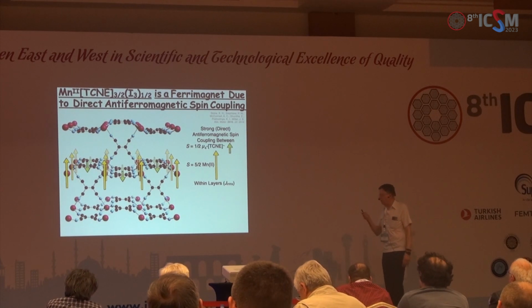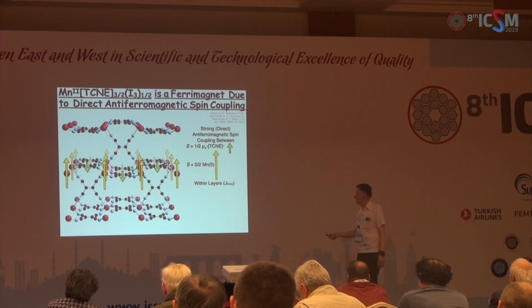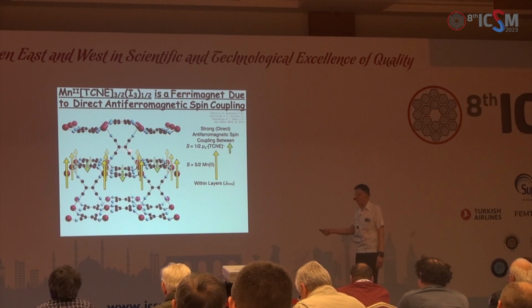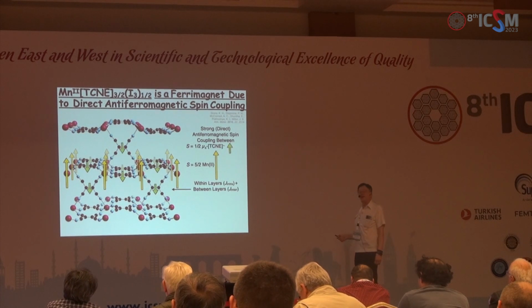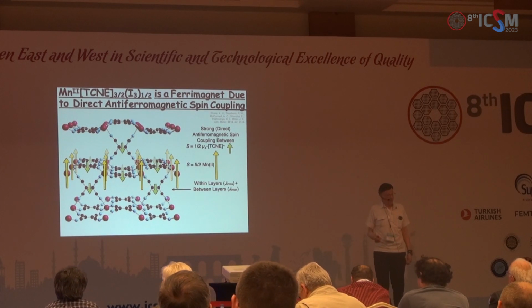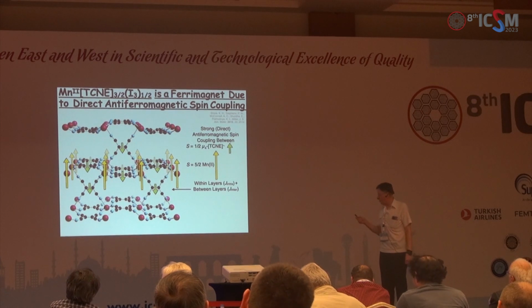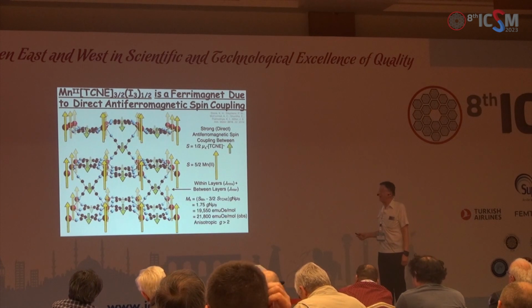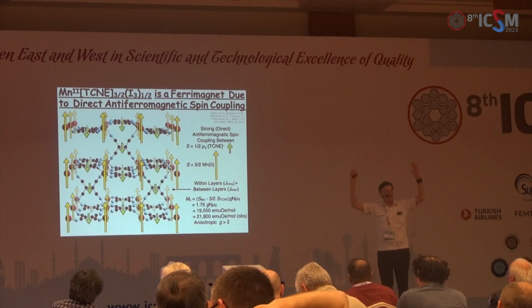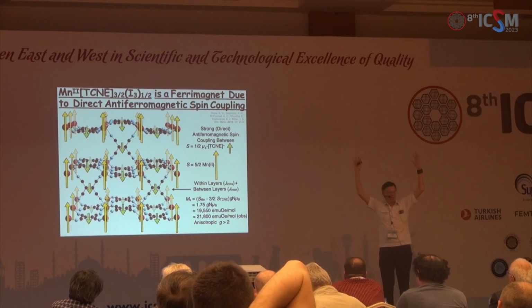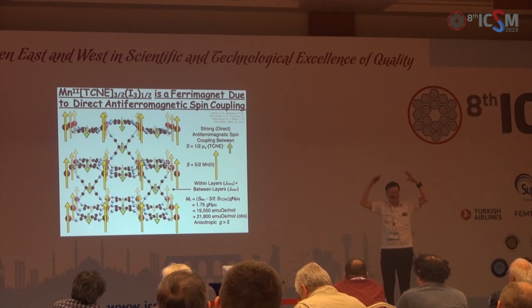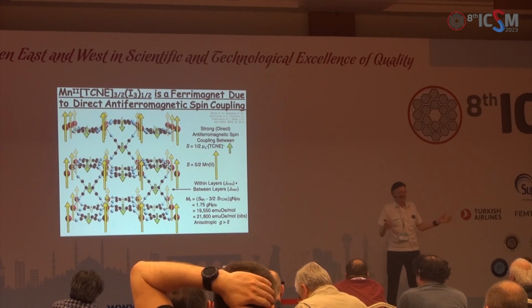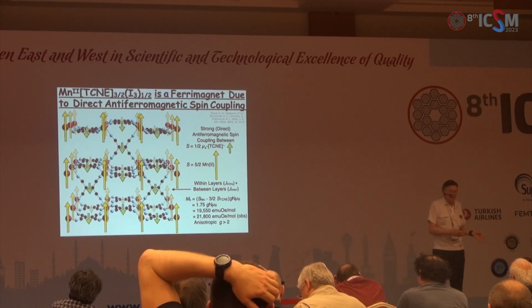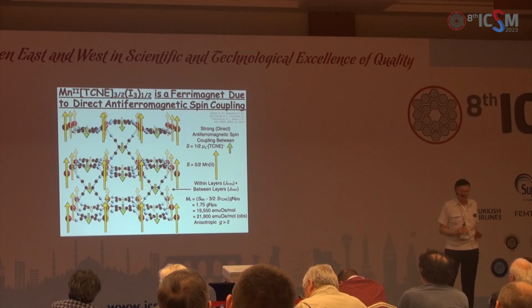But instead of coupling to the next layer through a diamagnetic one, here's a spin over here, a radical anion. So they have another spin, and that spin couples antiferromagnetically to all its manganese neighbors. So the entire 3-dimensional bulk material has manganese spin up, TCNE spin down, 5 halves minus 1 half. It orders as a ferrimagnet and doesn't have the coupling through the non-magnetic layer that would give you an antiferromagnet.